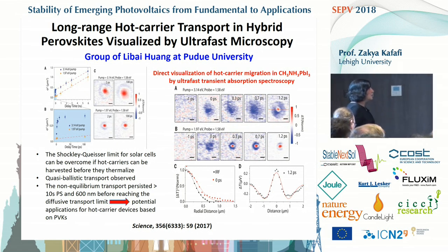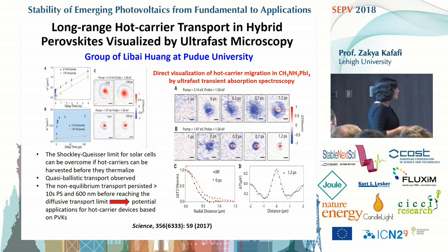Long-range hot carrier transport was also measured in hybrid perovskite using ultrafast microscopy. This is the group of Huang at Purdue University. The point here is that the Shockley-Queisser limit for solar cells can be overcome if hot carriers can be harvested before they are thermalized. In this particular material, they observed quasi-ballistic transport, and this non-equilibrium transport persisted for more than tens of picoseconds and 600 nanometers, which is a long way, before reaching the diffusive transport limit. So this opened the doors for applications for hot carrier devices based on perovskites.